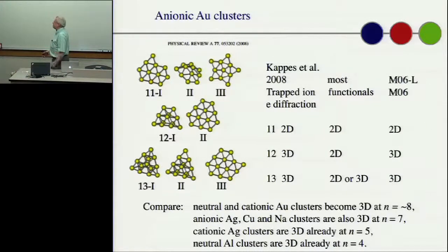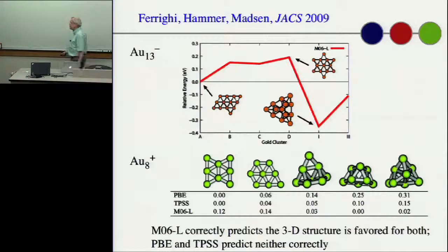Well, what happens? Most of these methods predict that you actually stay planar in the gold clusters up to a much larger number. But we get the transition at the right place. Here was another paper. Here's a repeat of the gold 13. You can see this planar structure here. You can see a planar structure there, but you can see this 3D structure is lower. Here's the gold 8 with the cations, and you can see a variety of different structures.